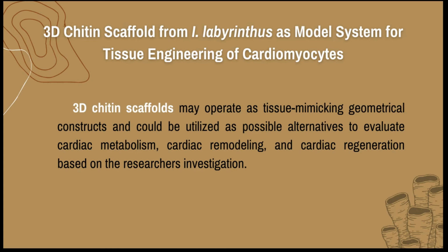These characteristics, together with the capacity to expand with a range of liquid in a matter of seconds due to capillary effect, and structural stability after sterilization up to 200 degrees Celsius, may be enabled for practical use of such scaffold in regenerative medicine, employing tissue engineering principles. I. labyrinthus provides a ready-to-use isolated flat 3D chitin scaffold that preserves its porous nature while being mechanically robust enough to be manipulated manually.